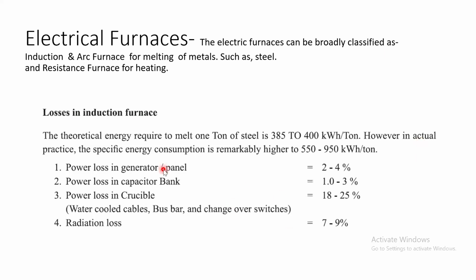So where is the rest of the energy? Power lost in the generator or panel is 2 to 4%. Power lost in capacitor bank is 1 to 3%. Power loss in crucible is 18 to 25%. Water cooled cables, bus bar and changeover switches. Then radiation loss is in the range of 7 to 9%. So the major loss in this induction furnace occurs while heating in the crucible where the metal is heated. So this loss is around 18 to 25%. So the efficiency of electrical furnace is in the range of 60 to 70% because of all these losses, which can be shown even on the Sankey diagram, which we have learned in the previous topic.